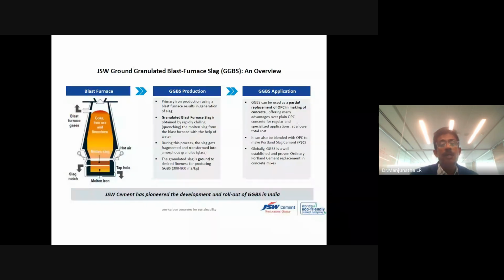So once the blast furnace slag is taken out and quenched into small granules, after removing moisture, we have a vertical shaft grinding mill or a ball mill. You grind it into fine powder. That's called GGBS, ground granulated blast furnace slag. That can be blended along with OPC cement to make slag cement, and otherwise that GGBS can be sold